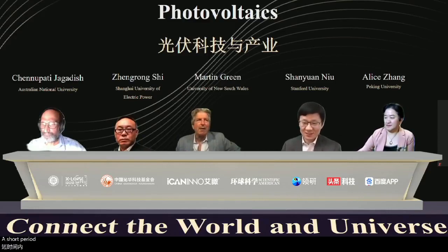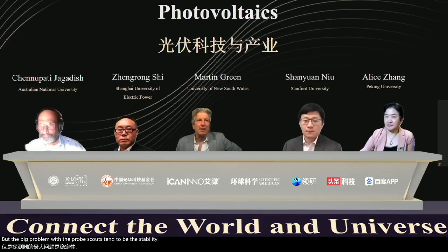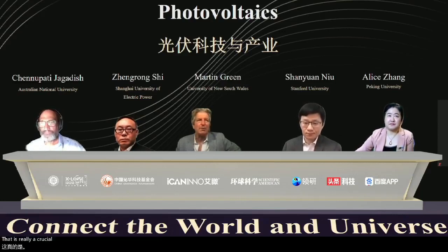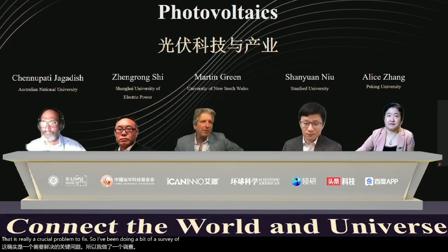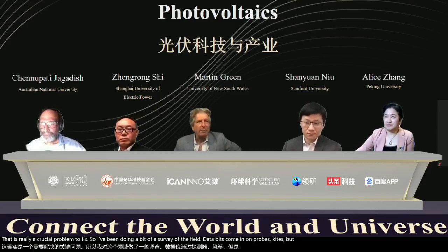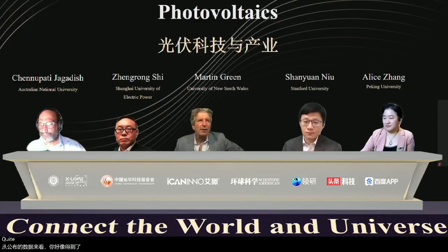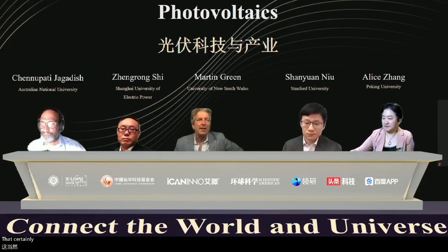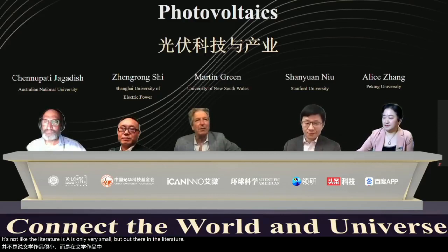But the big problem with the perovskites tends to be the stability. That is really a crucial problem to fix. I've been doing a bit of a survey of field data that's come in on perovskites, and from the published data, it seems like you're getting quite serious degradation over periods of weeks rather than months or years. The last 3 reports I've seen have reported, like, 20% degradation over 20 days, something like this. There are many companies talking about commercializing, so maybe some of those companies are doing better, but certainly out there in the literature, and there's an enormous literature on perovskites, anyone who has attempted outdoor testing of the perovskites has reported quite limited durability.